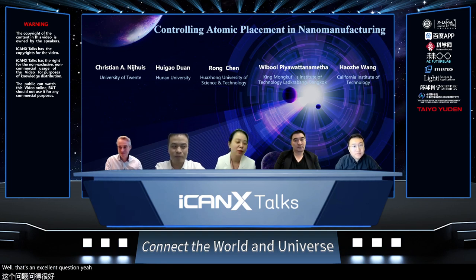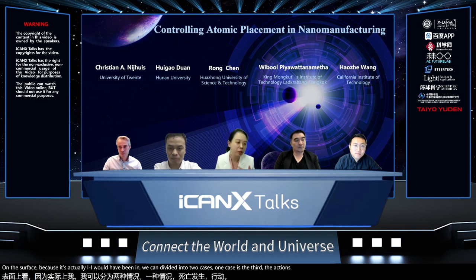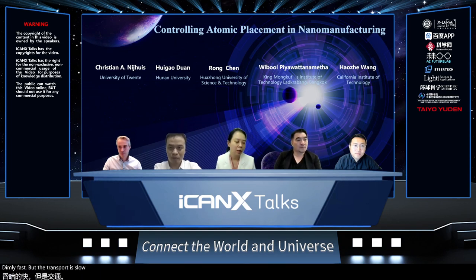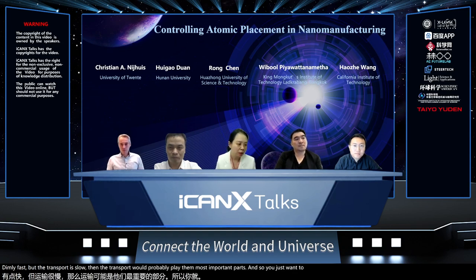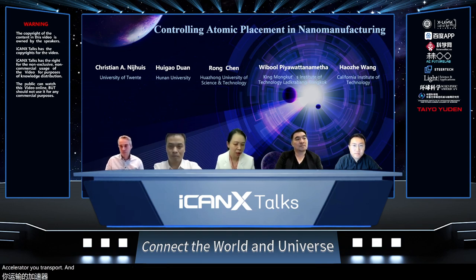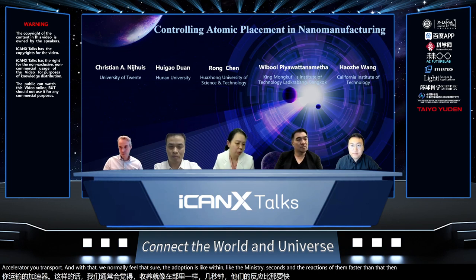Especially from the manufacturing point of view. The theoretical speed, I would say, is how fast it can be absorbed on the surface. I think we can divide it into two cases. One case is that the reaction is extremely fast, but the transport is slow. Then the transport would play the most important part, so you just want to accelerate your transport. With that, we normally find that the absorption is within milliseconds, and the reaction is sometimes faster than that, then you will be able to obtain that.